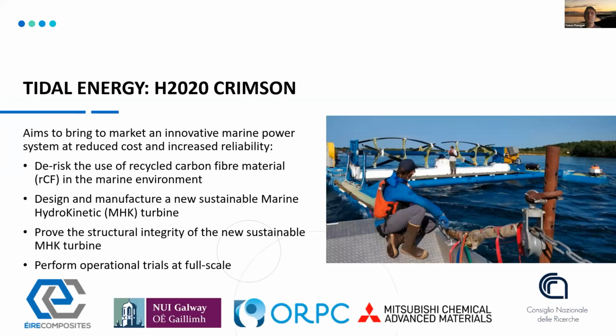This is the Crimson project on tidal energy. The picture in the background is a tidal turbine, which has helical blades, which were manufactured at Éire Composites. The green parts, the struts, were made with glass fiber and powder epoxy, and the black parts are carbon fiber powder epoxy. They're helical blades, and the whole device is about 10 meters long, so it's 2 by 5 meter sections. That's an existing device that's been installed in Alaska and operated successfully for 2 years.